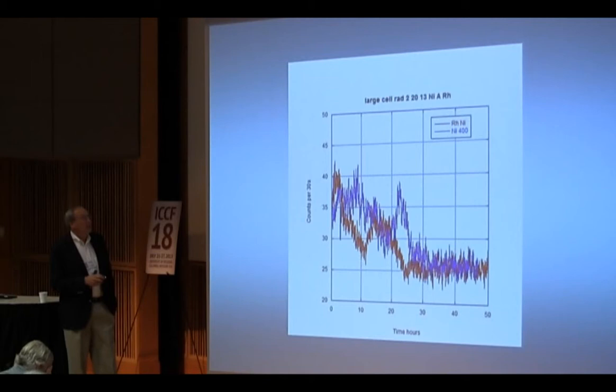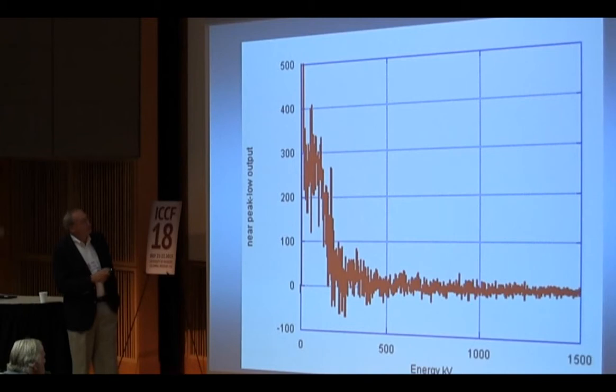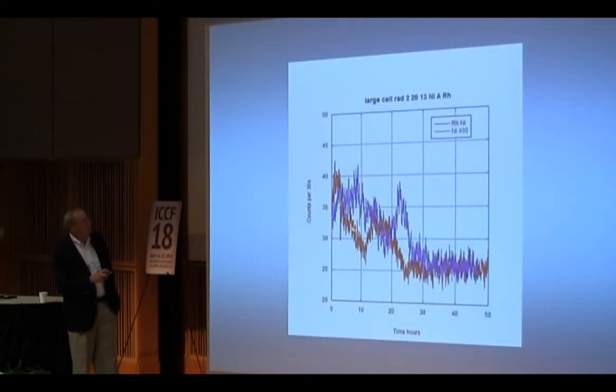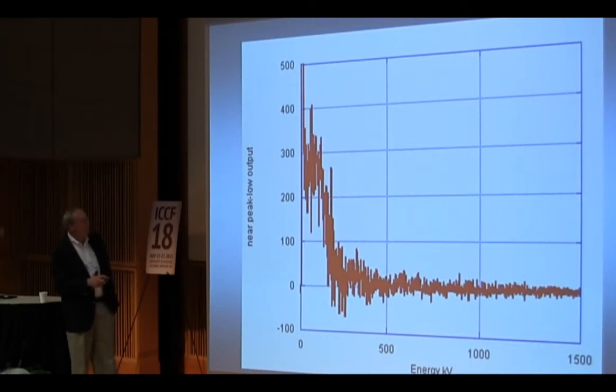Now, this is actually radioactive emissions. And the next slide is the time dependence of that. So we're dropping. We don't want to count this after 24 hours because you're not going to see much. But this is the difference in the two spectra that you just saw back there. One is out here at the extreme time, and then very close in, we were taking these radiation measurements. So take the difference of the spectra at those times, and what we see is something here, maybe 200 kilovolts and below, is what we're looking at.